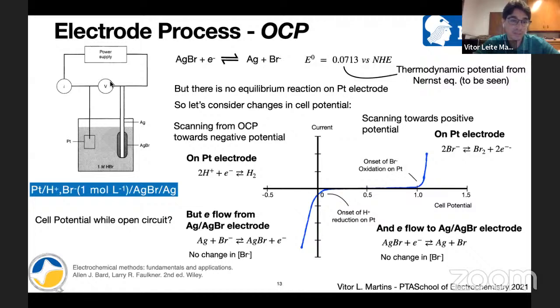The only thing that we will measure is the difference of potential between these two electrodes. And as we don't have an equilibrium reaction occurring in this electrode, it could be any value between the potentials where there is no reaction occurring at that potential, right? So if you go to 0 volts here, what do you have? We have hydrogen reduction. So it can't be 0 because for the potential in the platinum electrode to be 0, you need to have a flow of electrons.